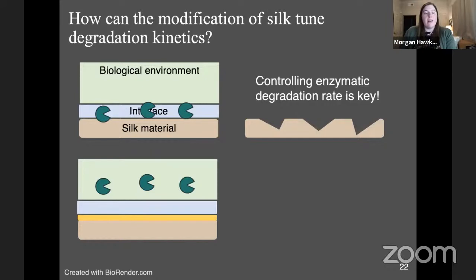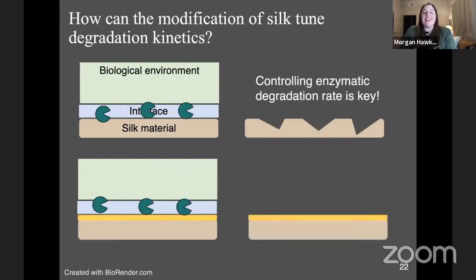So the goal of this project is to control the enzymatic degradation rate by controlling the surface properties of the material. And we thought that one way to do this would be by plasma depositing a thin hydrophobic coating on the silk, which might act as a barrier and may prevent enzymes from accessing the surface, thereby preventing the silk from degrading as quickly. So that's kind of an illustration of our hypothesis.